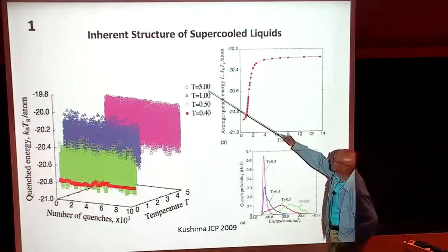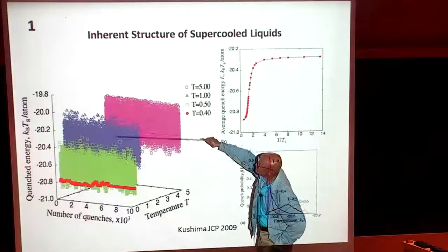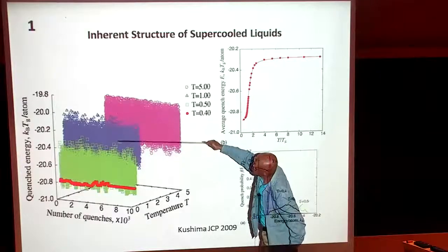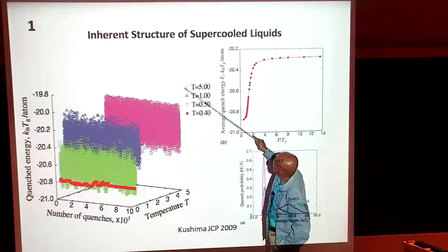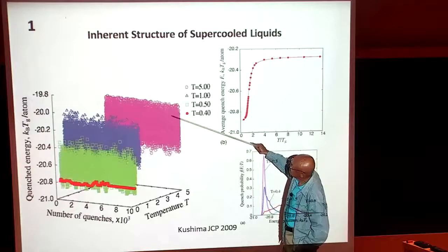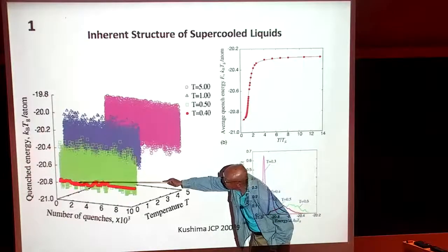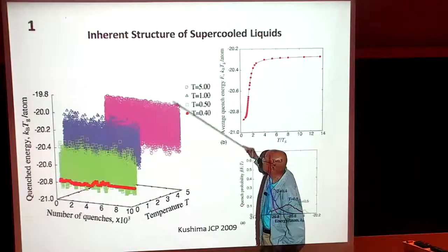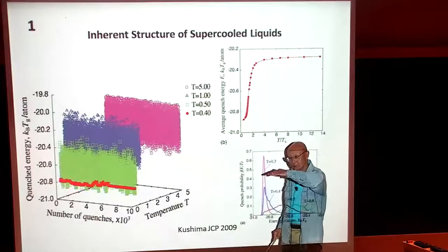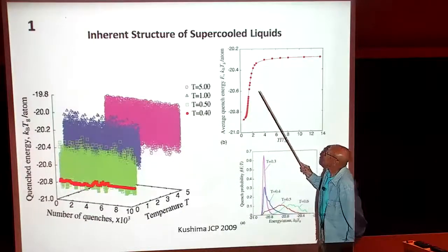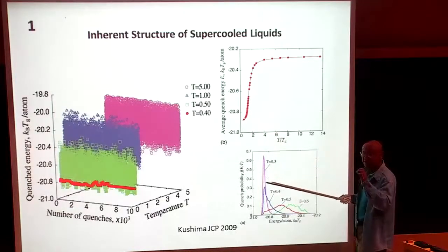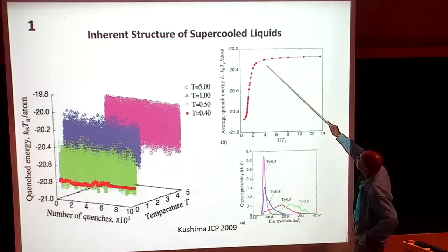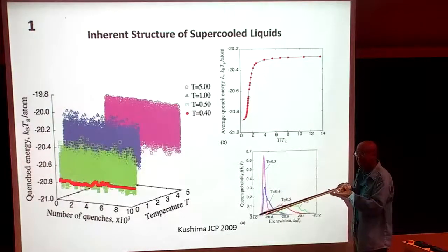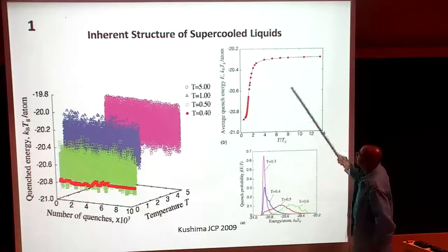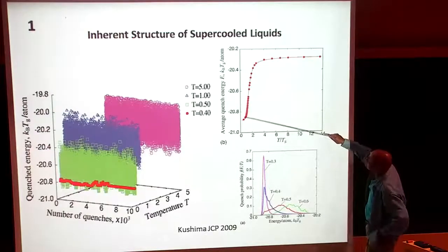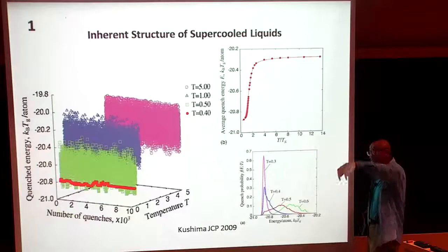So what's important is to say at high temperature you have a spectrum of energy that is very, very broad. And then when you get down to low temperature, you can see now it is very, very narrow, but at very, very low energy. That means when you lower the temperature, when you do the steepest descent quench at lower and lower temperature, and you measure the energy landscape by an average, you find a high value at high temperature, which means whatever wells you have are very shallow, and it's very easy to go back and forth. You go through this very steep change, you drop down to a very low, very deep average value, which means now you're getting very sharp wells.